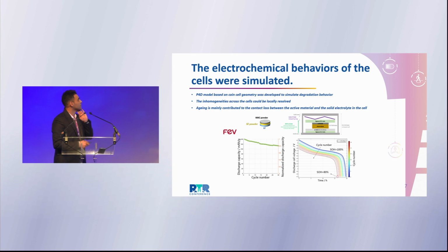Then the last step was also simulation. So we did P2D modeling at coin cell level to see what is the main reason for degradation of these cells. The main outcome of this modeling was that in the first step, we have some reduced capacity because of the decomposition at electrodes. However, after cycling, this capacity fade is mainly attributed to contact loss of materials, for example, contact loss of the cathode particles with solid electrolyte or binder, or in general, the loss of this active material.